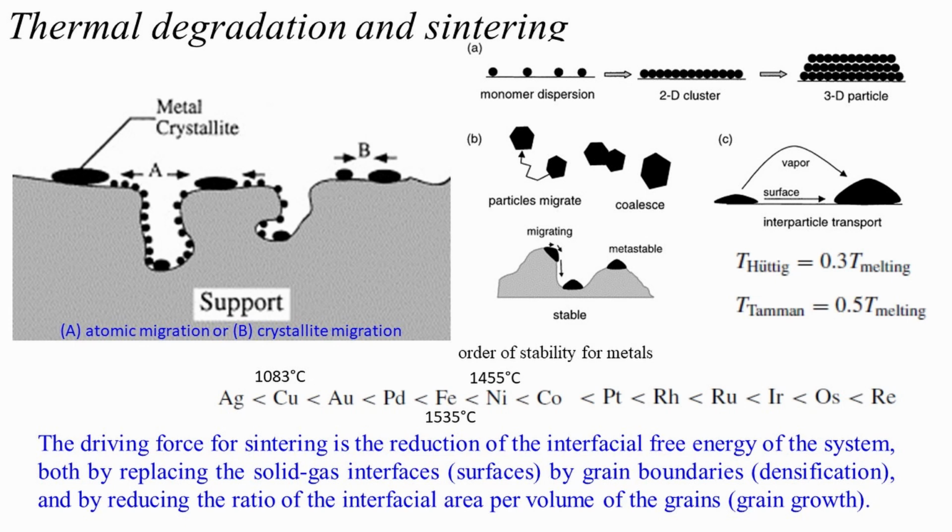Redispersion of metal particles can occur in the presence of oxygen or chloride, and the process may involve formation of volatile metal oxide or metal halide complexes which attach to the support and are subsequently decomposed to small crystallites upon reduction. Another way is formation of oxide particles or films that break into small crystallites during subsequent reduction.